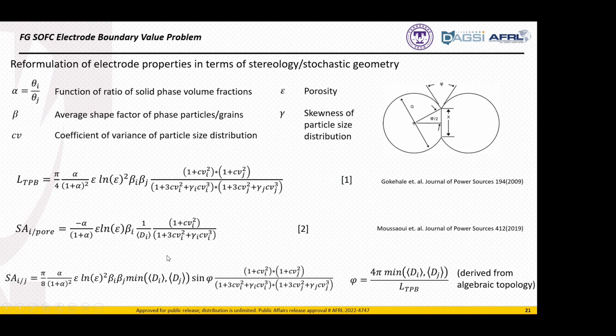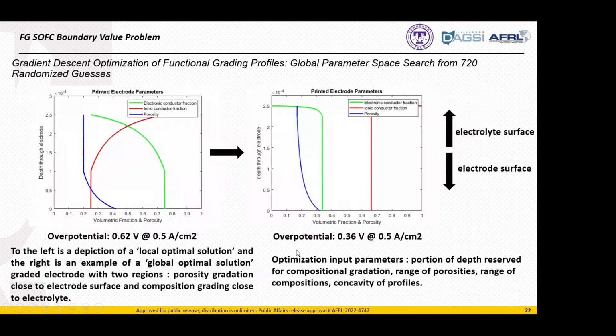One equation that we've kind of added here to the field. So previously, folks had derived equations for the triple phase boundary and the specific area of a phase with the pore space from literature. And we have derived this new expression here, which will give me the interfacial area between nickel particles or between like particles of the same phase, or the areas between particles of two separate phases. But I can go into that in more detail if anyone is interested later.